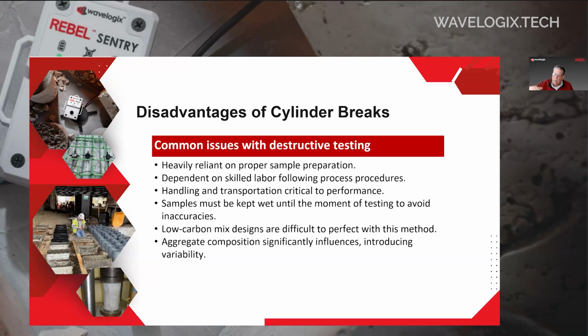Then you fill it again, pour it, you rod it again, you pound it, and then that's one cylinder. And you do that 15 times. It's a pretty laborious process. And you can imagine that after a while, you get tired of not rodding enough or not pounding it properly. And if you don't follow that procedure, there's a potential that that cylinder is made wrong. And if it's made wrong, it's not going to give you accurate compressive strength when you go to crush it.